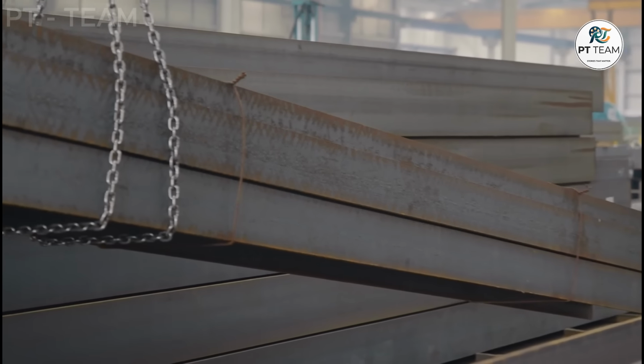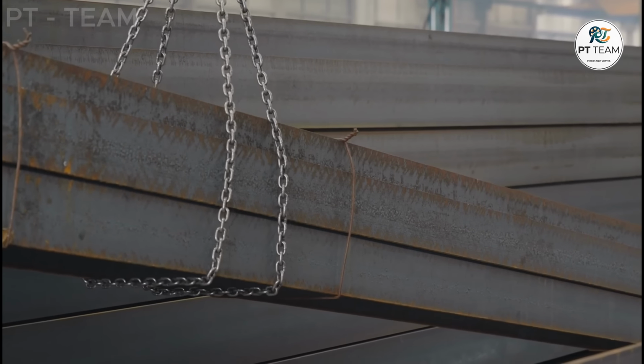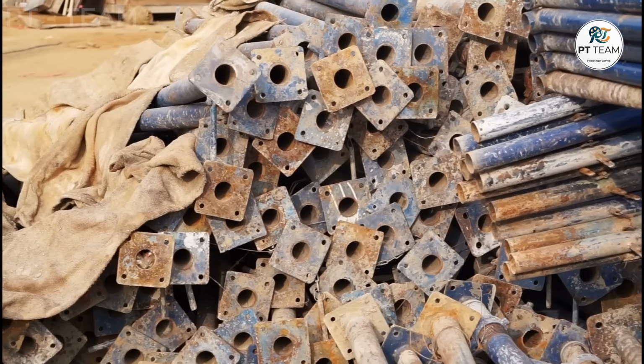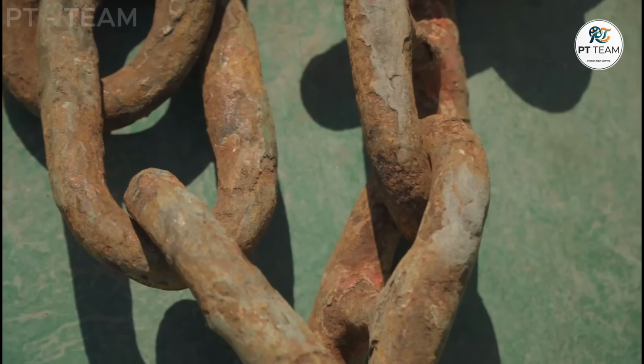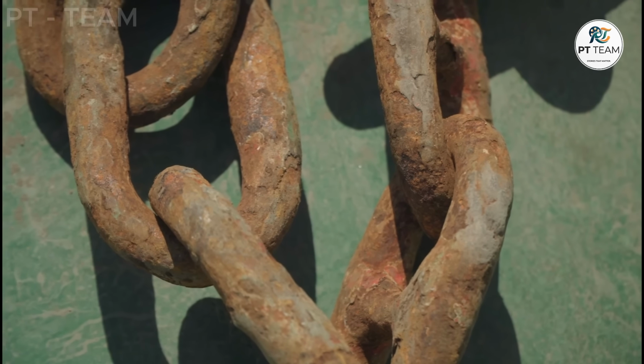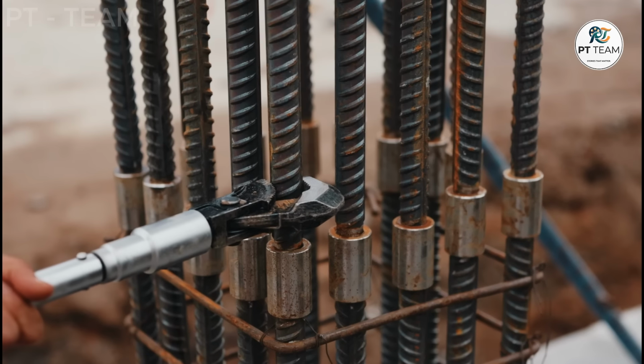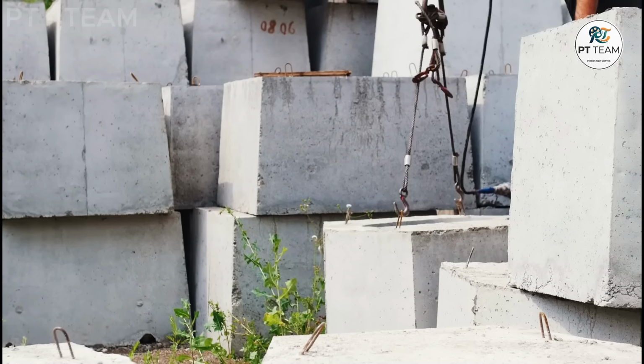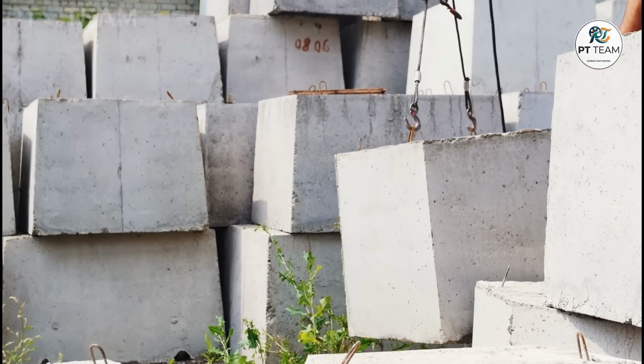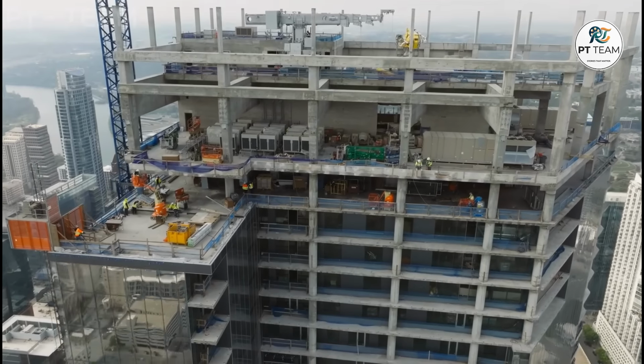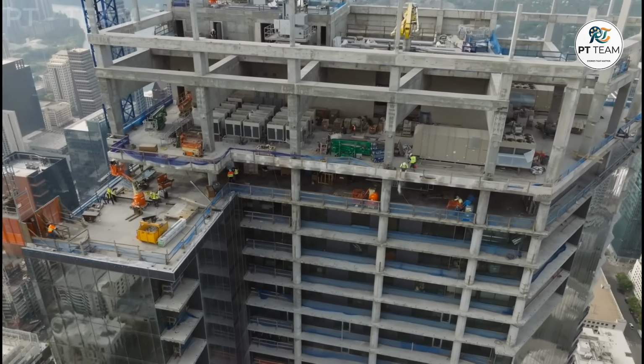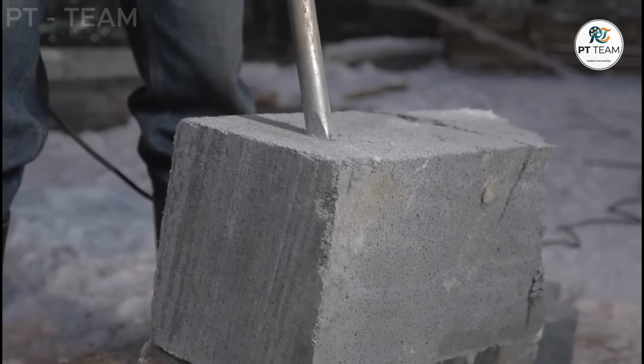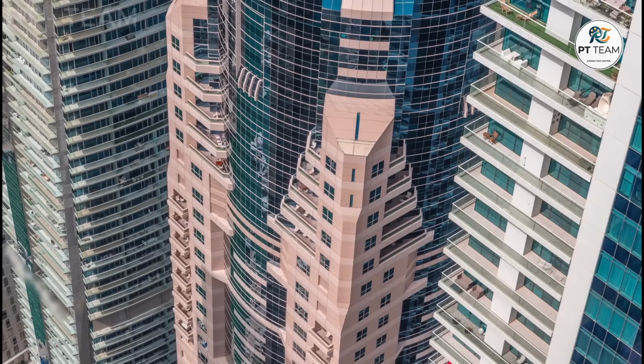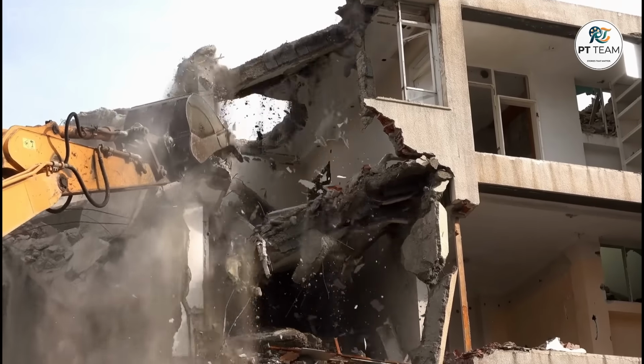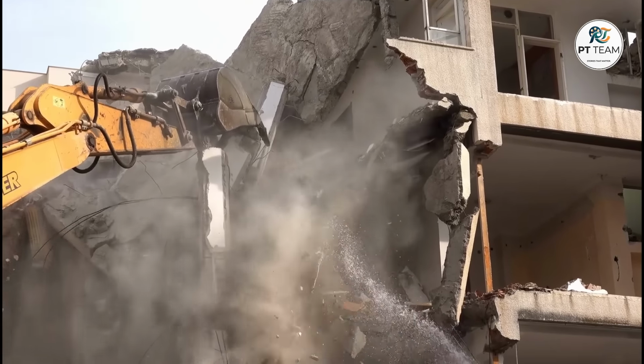The byproduct of this corrosion process occupies significantly more volume than the original steel. Depending on the specific type of iron oxide formed, the rust can take up to 6 times as much physical space as the metal it replaced. The steel bar is effectively trying to grow in size while being tightly clamped inside a solid block of stone. This expansion generates an immense outward pressure against the surrounding concrete. Concrete is incredibly strong when you push down on it, which is why it can support the weight of a 100-story tower. But it is notoriously weak in tension, meaning it breaks easily when you try to pull it apart or push it outward from the inside.